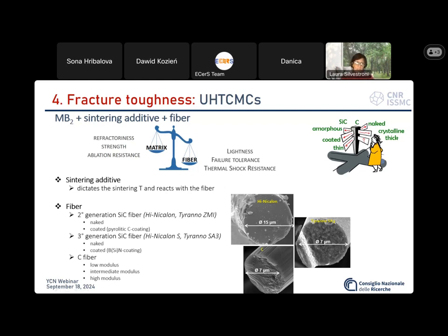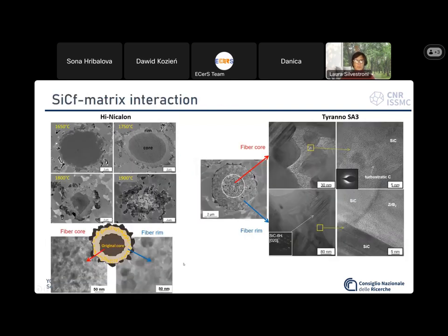And it's very possible that before measuring a considerable fracture toughness increase, you will have to pay attention to several factors. First of all is the sintering temperature, which is dictated by the sintering additive, and will create some troubles with the fibers, which you find in several generations, more or less crystallized. And every generation, every type of fiber, also carbon fiber, has a different reactivity. So it's not really straightforward. Here you can see some examples of the interaction between silicon carbide fibers of second generation, the Hi-Nicalon, and the third generation Tyranno SA3 with the same matrix, and you can see how these fibers progressively deteriorate with increasing sintering temperature. So it is a bargain between the matrix densification and the fiber degeneration.